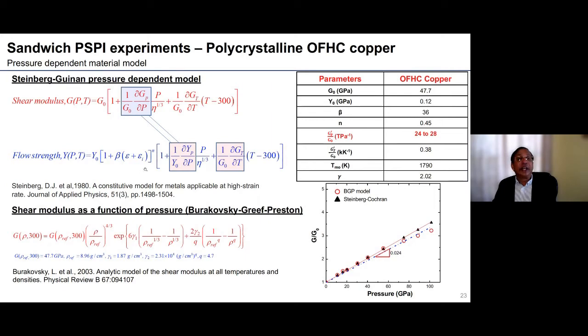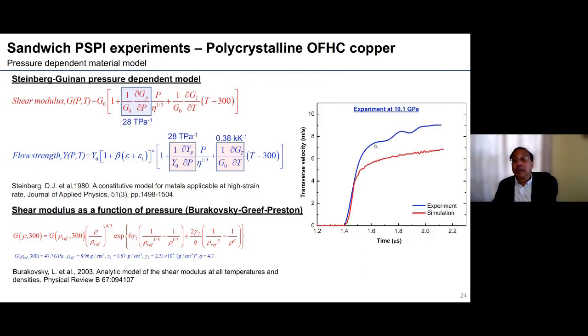Now, the flow strength, on the other hand, is again described by the variation of the flow strength with respect to pressure, and also the shear modulus with respect to the temperature. So one of the assumptions made in the Steinberg-Guinan model is that the variation of the shear modulus with the pressure and the variation of the yield strength with pressure are assumed to be one and the same. But when you make this assumption, we were not able to match the experimental results. If you assume that these two are the same, which is the usual assumption and the literature value, quoted as 28 per terapascal, then we are not able to match this transverse velocity. As I mentioned, the transverse velocity provides an excellent constraint on the strength model for the material.